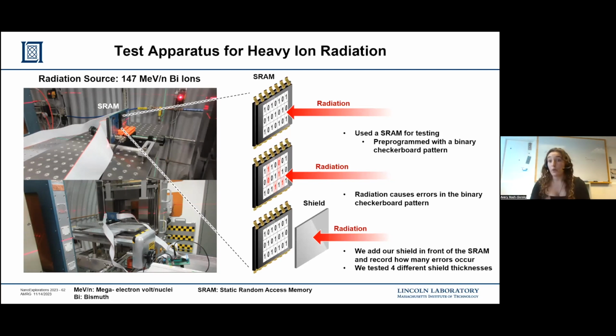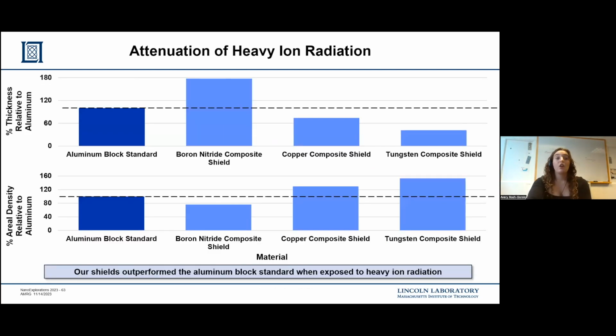This we tested for 4 different thicknesses for our copper, boron nitride, and tungsten shields, and then compared it to 4 different thicknesses of our aluminum block standard. So the way we measured this was we wanted to see what thickness was necessary for 0 errors to be thrown on the SRAM. And then we normalized this thickness to our aluminum block standard. So that's 100%. When we use thickness as our metric, both our copper composite shield and our tungsten composite shield outperform the aluminum block standard.